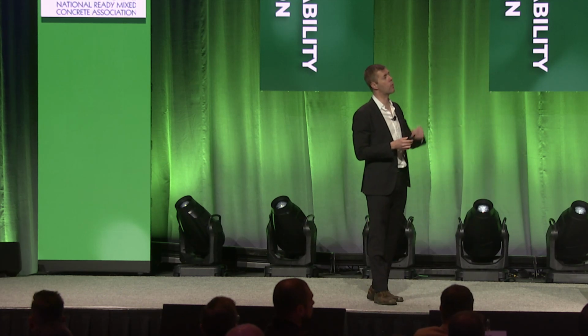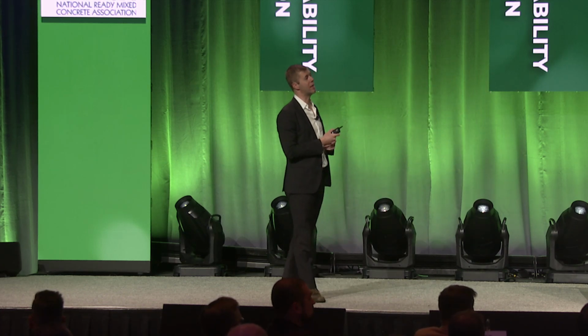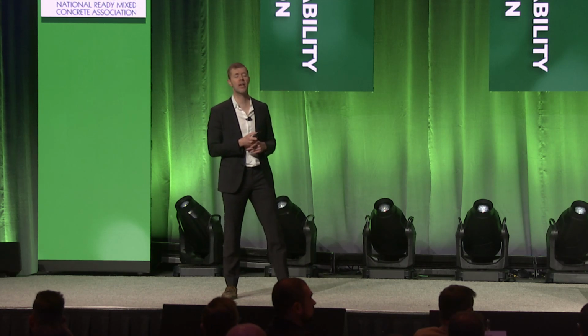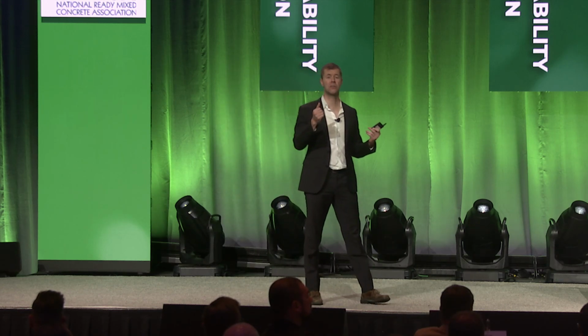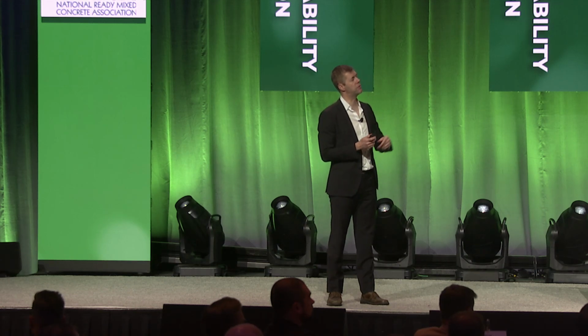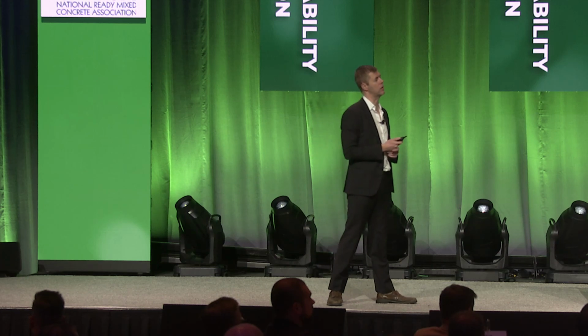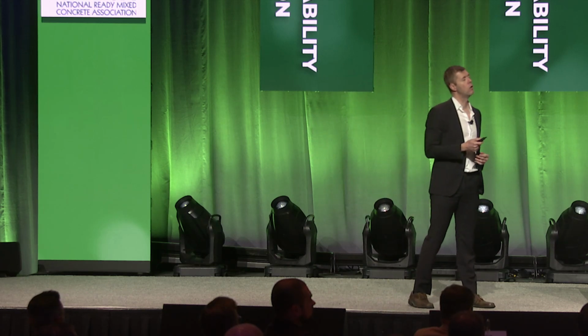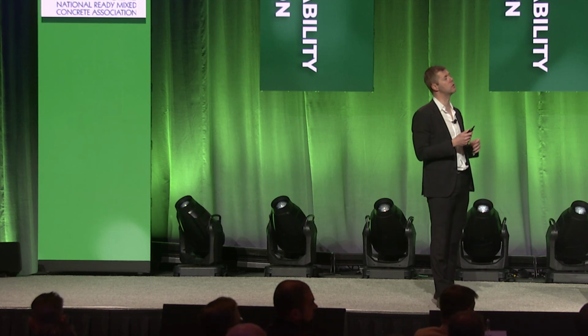That's not good. Upper right-hand corner. Upper left-hand corner, that's not good. Deficient amount of fine sand. How do you fix that? They add more paste. They add more cement. They add more whatever else to the mix. Lower left, excessive intermediate aggregate. It's kind of segregating coming out. Lower right-hand side, excessive coarse aggregate, again, is kind of coming out of the mix. And right in the middle, it's just right.